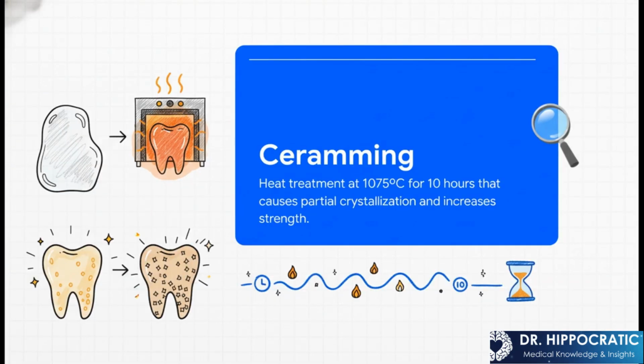Now here's where the real magic happens. It's a process called ceramming. See, the crown starts out as basically a piece of clear, pretty fragile glass. To make it tough enough to be a tooth, it gets baked at over 1,000 degrees Celsius for 10 solid hours. And this isn't just baking, it's a total transformation. That intense heat forces this whole network of microscopic crystals to grow inside the glass, turning it from something that would shatter in a second into a really strong tooth-colored ceramic. This step is the secret to the whole thing's strength.